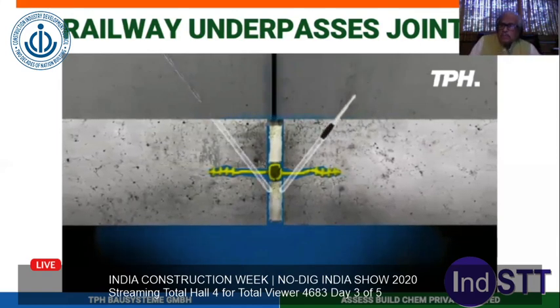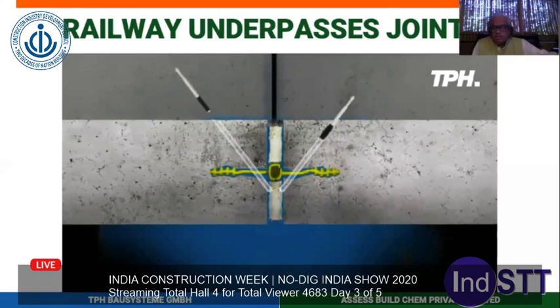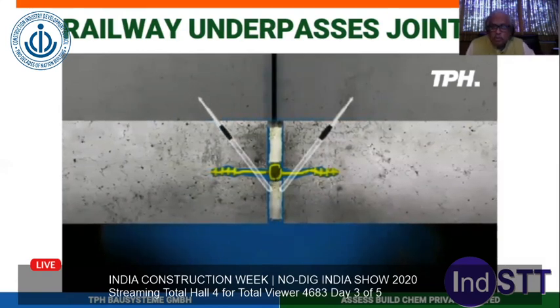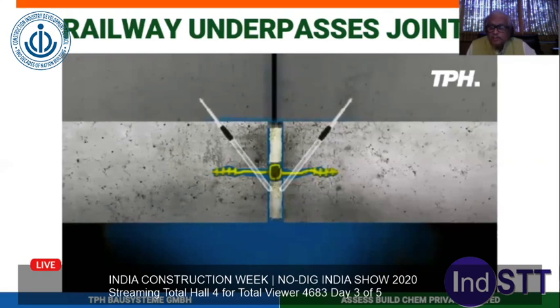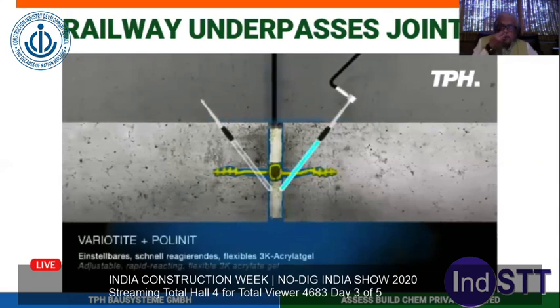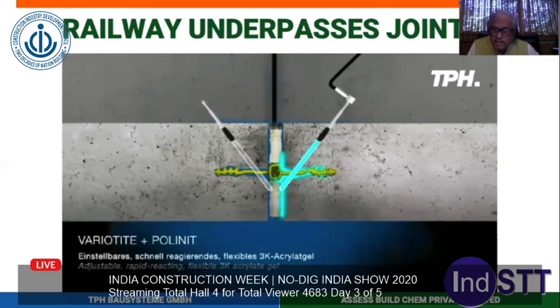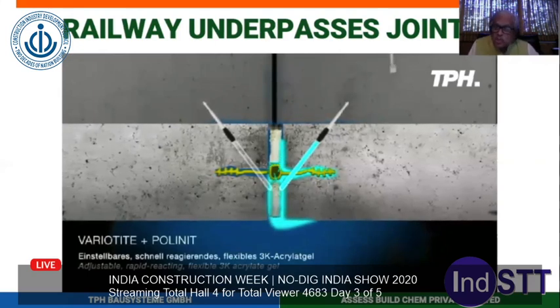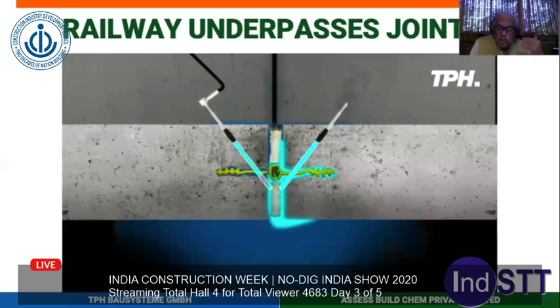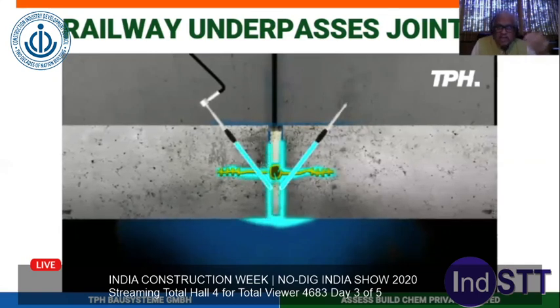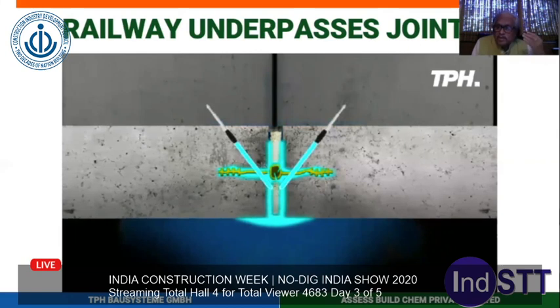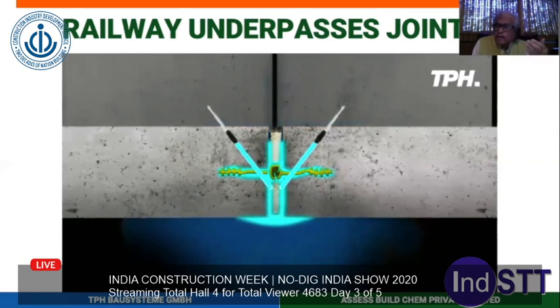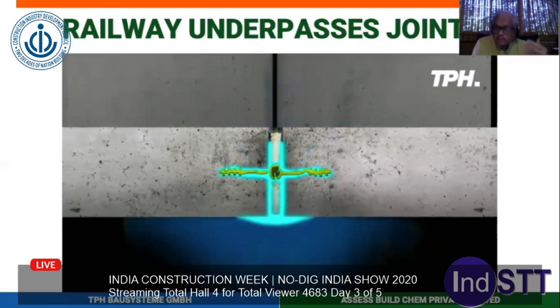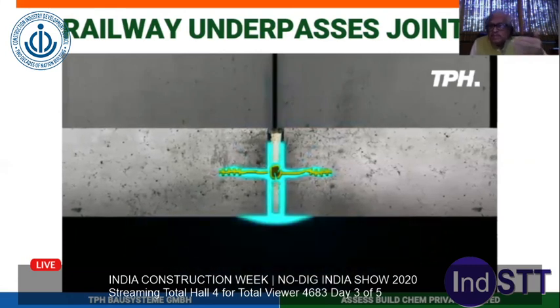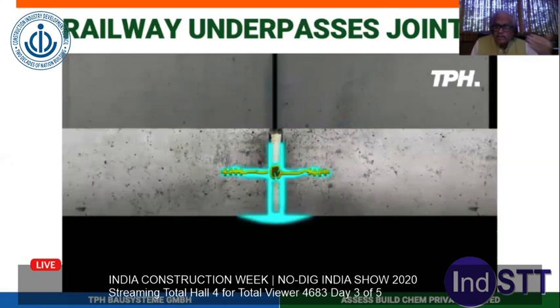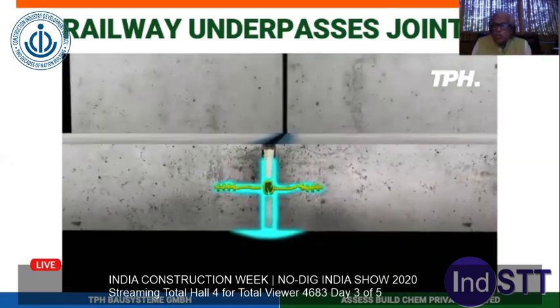There are suggestions from people saying that you use only foam, no problem. It is stopped. Of course, it will be stopped for 2 months or 4 months or 6 months, because foam is not a permanent material. Some people say you put some other polyurethanes inside, rigid or flexible polyurethanes. No, this won't help either, because you have to create a joint sealing material. A joint sealing material should have adequate bonding on the sides, enough elasticity for expansion and contraction, and it should become a seal. So any other method won't work.